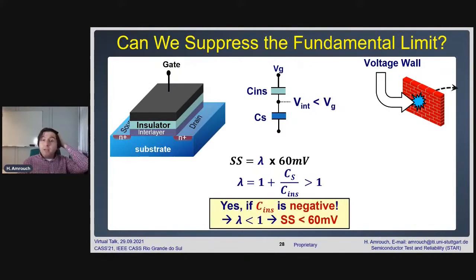In fact, yes, if we could achieve a negative capacitance. Why? Because if you look to this constant factor, the lambda, it's 1 plus something. And as long as this term is positive, we always have higher than 60 millivolt per decade. But if we could make it negative, we could actually make the lambda smaller than 1. And if it's smaller than 1, then we could actually push the subthreshold swing to go below 60 millivolt. But do we have a negative capacitance in nature?